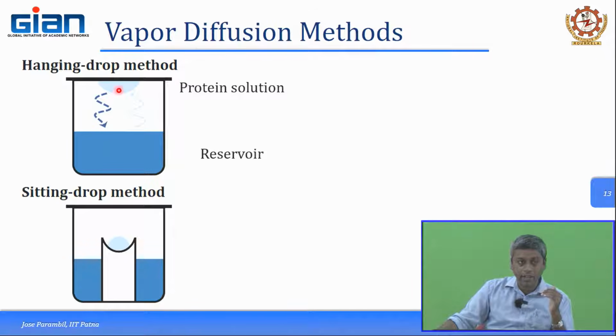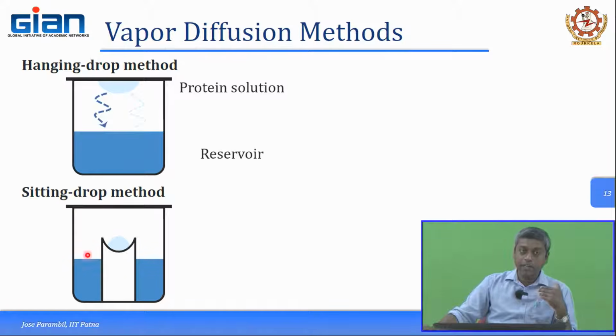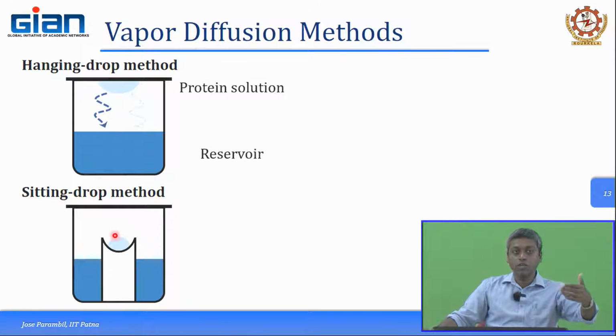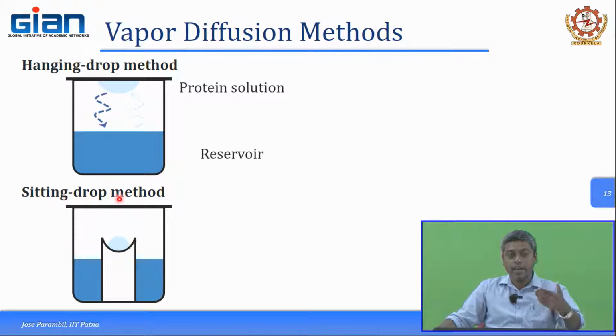This would mean that over time the volume of the protein solution would keep decreasing in the hanging drop. Same thing happens in the sitting drop as well. Water evaporates from both the reservoir as well as from the drop, but due to the equilibrium a gradual shift in the composition would take place, in the sense more water would evaporate from this droplet and less would condense back into it, whereas in the reservoir less would evaporate and more would come into it.